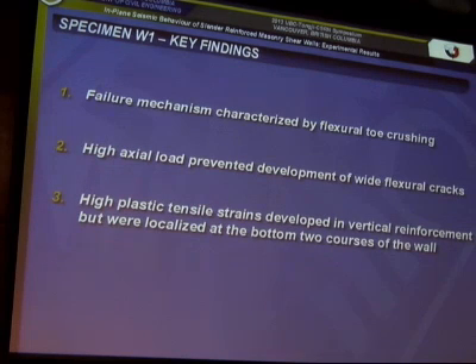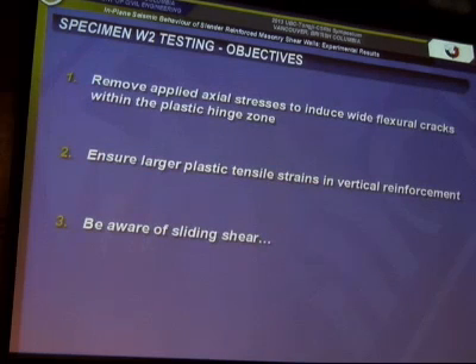Really, it wasn't what we were looking for, and the high axial load prevented the important development of wide and uniform flexural cracks over the plastic hinge height. Even though there were high plastic tensile strains, these were quite localized in the bottom two courses of the wall, which was not enough.